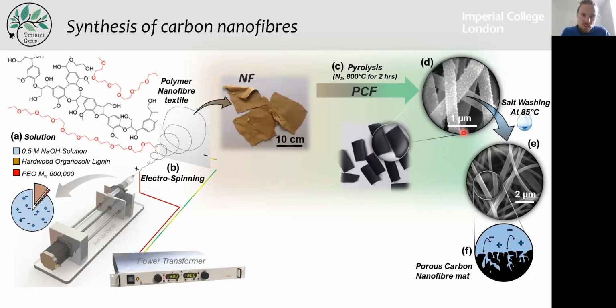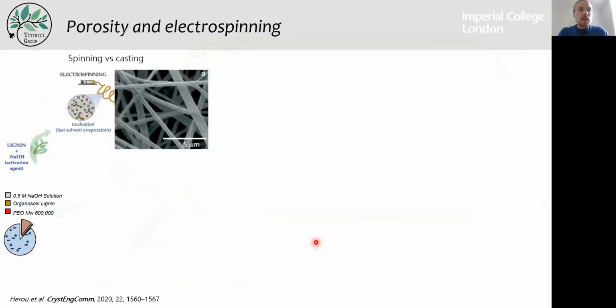And then we do a pyrolysis. We obtain this fiber surface, and that is the NaOH salt that is activating the fiber that still remains on the surface. So we wash it by putting the mats in water at 85 degrees. And then what we obtain is a porous carbon nanofiber. We've been trying to look at what the interaction is between the sodium hydroxide and the lignin. So by using this solution, we electrospin it, and just after electrospinning, we start observing loads of small crystals on the surface of the nanofibers.